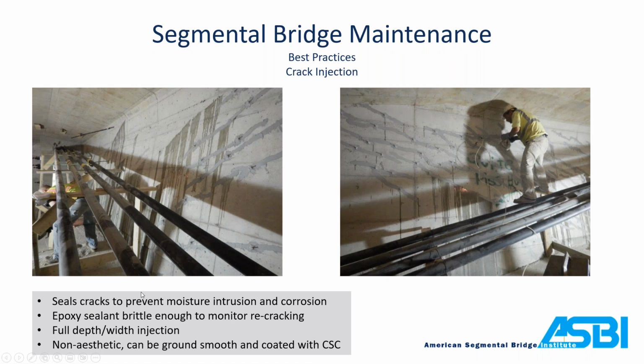It seals these cracks up, keeps the moisture from getting inside. You can see this guy here, he's doing the crack injection. First step is to place these ports along the crack. We typically space these the distance of what the web depth is. So if you have like a 2-foot web wall, you want to space these ports 2 feet because the epoxy will move in a 360-degree circle. So as you pump into this first port, once the epoxy starts oozing out of the second port, you know you got full depth penetration of that epoxy through the entire web of that slab.